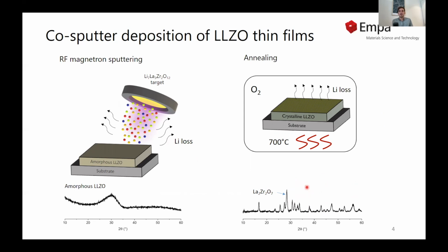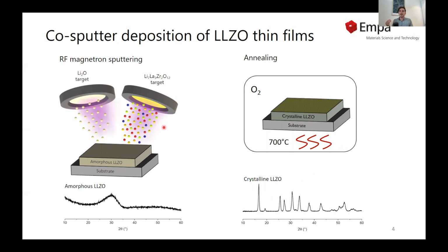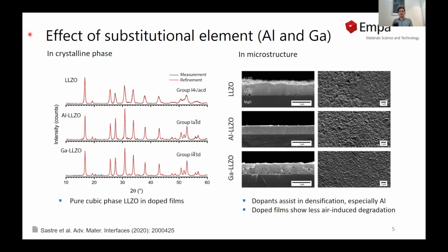In order to compensate the lithium losses and achieve a pure LLZO crystalline phase, we included an additional source of lithium, a lithium oxide target, which is co-sputtered during the deposition process. With this, we are able to achieve a pure crystalline LLZO phase. Pure LLZO crystallizes in a tetragonal phase at room temperature, which is not a good ionic conductor. In order to become a high ionic conductor, it requires the addition of a substitutional element, for example, aluminum or gallium, that stabilizes its cubic phase at room temperature.